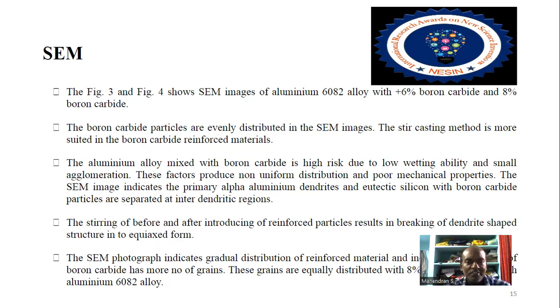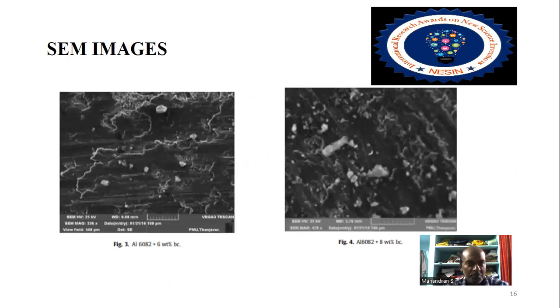And the images indicate the primary alpha aluminum dendrites and eutectic silicon, with boron carbide particles separated at interdendritic regions. The stirring before and after introducing the reinforced particles shows the breaking of the dendrite-shaped structure into equiaxed form. The SEM photograph indicates gradual distribution of the reinforced material, and boron carbide has a larger number of grains. These grains are equally distributed with 8% boron carbide in the aluminum 6082 alloy. These are the same images noted.